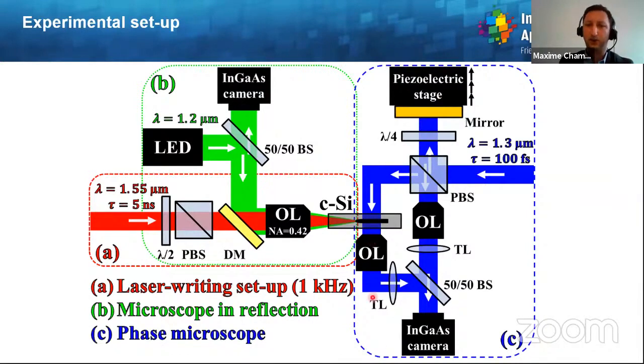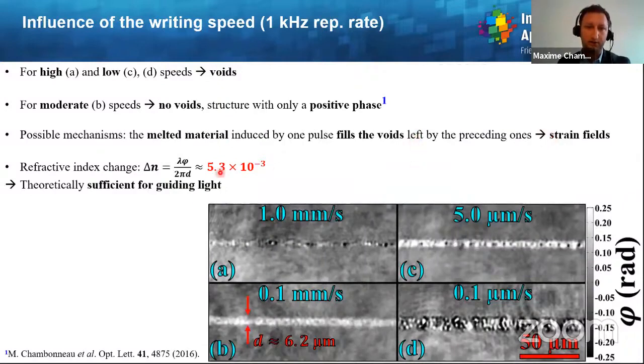And besides, we have another diagnostic, which is represented here, which is nothing else than a Mach-Zehnder interferometer, which is at least transposed to the infrared at 1.3 micron wavelength, and it allows us to have phase images. So what is the phase shift of the laser-induced modifications, which are essentially related to the refractive index change. Then here are some typical results we obtain when one tries to